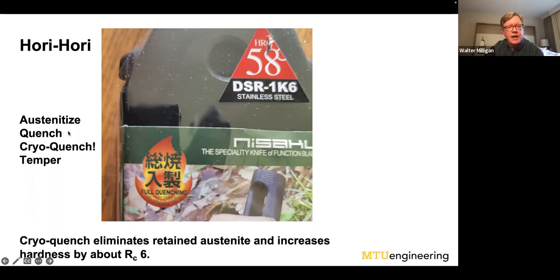But then, because of the composition of the steel, we don't get rid of all the austenite if we just stop at room temperature. And so that austenite that stays in there will not temper, and it will end up being a soft phase in there, and it will hurt the performance. And so when they say full quench on this thing, what they mean is they actually had to cryo quench it. They had to put it in liquid nitrogen or in a bath of dry ice or something like that, depending on the temperature, to get rid of all the retained austenite. And then they temper it. And if you don't do that step, the cryo quench step, you're only going to get 52 Rockwell C, because the retained austenite is going to be a soft phase in there, and you're not going to get the full benefit of the material composition.